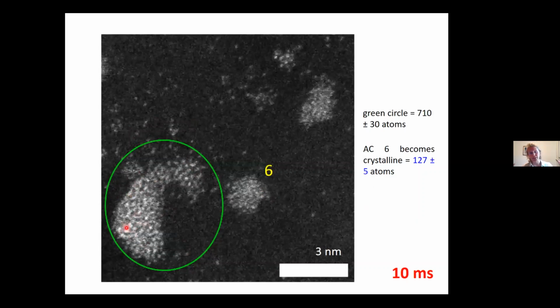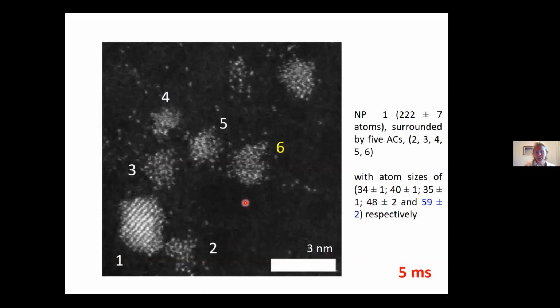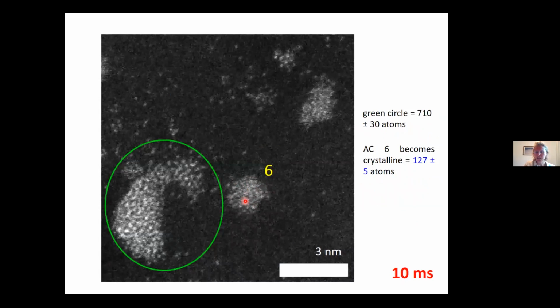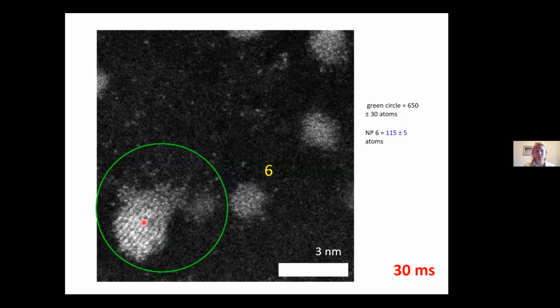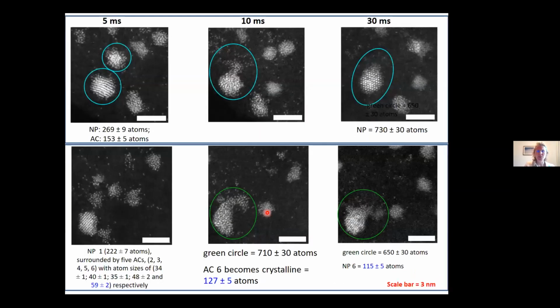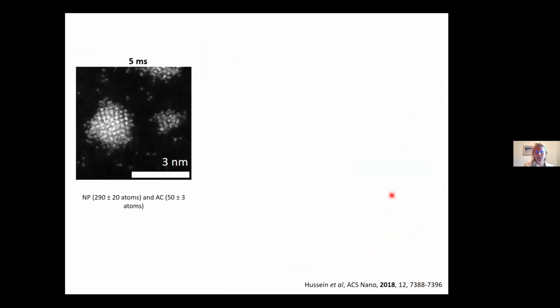And this nanoparticle, because it's suddenly got all these atoms coming onto it, has itself become amorphous. This particle here is keeping itself, and has started to go crystalline. It hasn't decided to contribute to making this structure get bigger. And if we follow it with further time, you can now start to see that amorphous structure recrystallizing out, okay? And you can see here, our particle 6 stays crystalline. So these are just images of the collective process at these timestamp locations, showing movement at the single atom level.